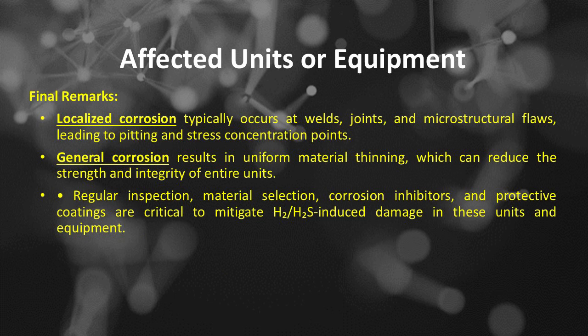The final remarks from high-temperature hydrogen (H2) and hydrogen sulfide (H2S) corrosion that we can take are included. Localized corrosion typically occurs at welds, joints, and microstructural flaws, leading to pitting and stress concentration points. General corrosion results in uniform material thinning, which can reduce the strength and integrity of entire units. Regular inspection, material selection, corrosion inhibitors, and protective coatings are critical to mitigate hydrogen (H2) and hydrogen sulfide (H2S) induced damage in these units and equipment.